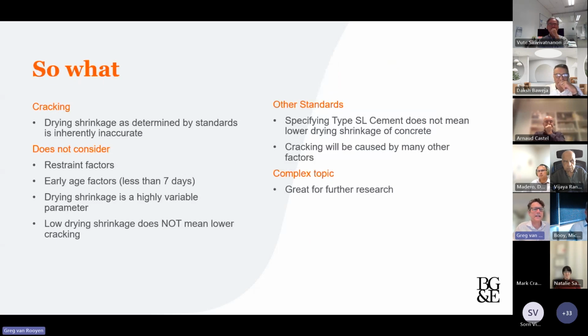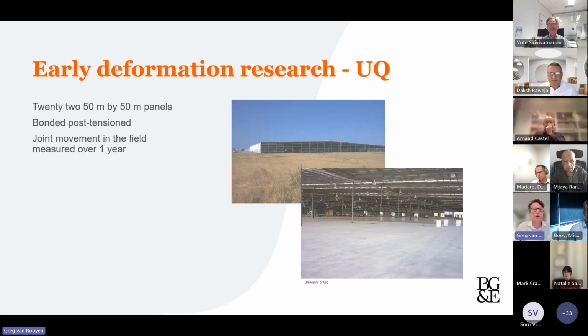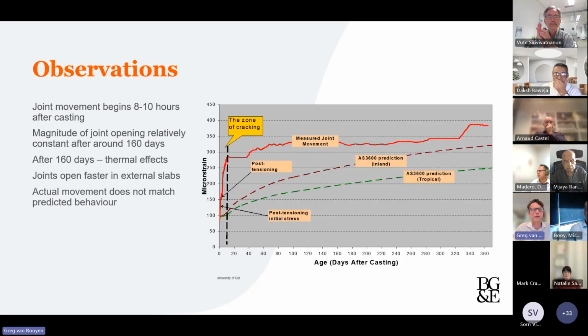From the standard, it doesn't take into account any restraint or shrinkage that may occur a lot earlier in the concrete, and specifying or requiring lower shrinkage doesn't mean lower cracking. So obviously a great topic for further research, and just as a lead into where we're heading, some work done a few years ago by University of Queensland on a large post-tension floor out here in Queensland. And this floor had strain gauges installed.